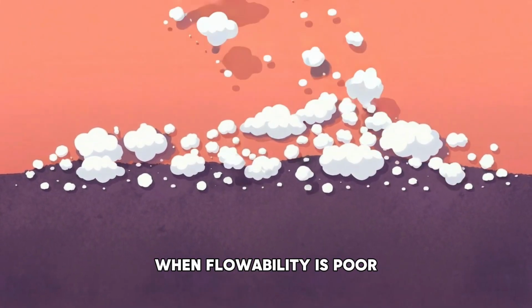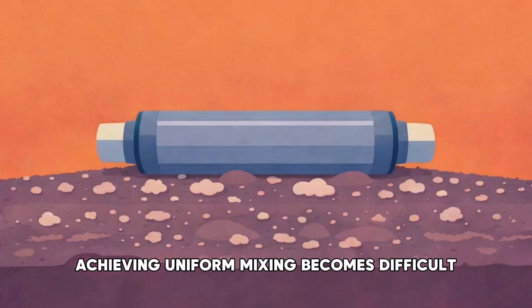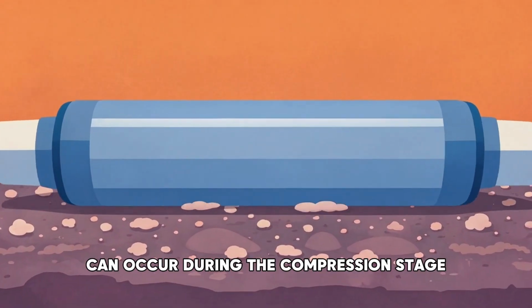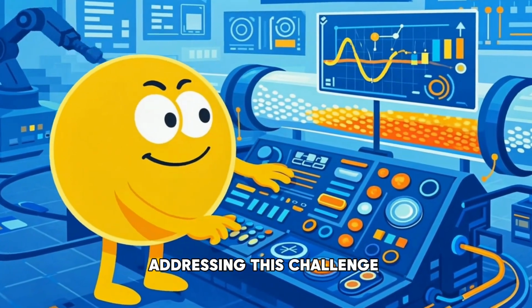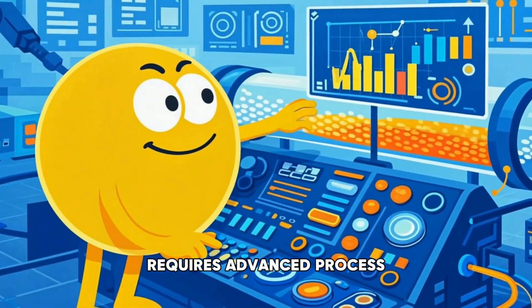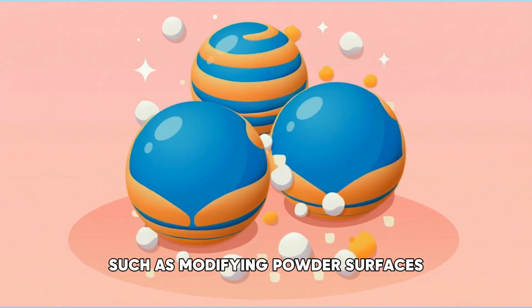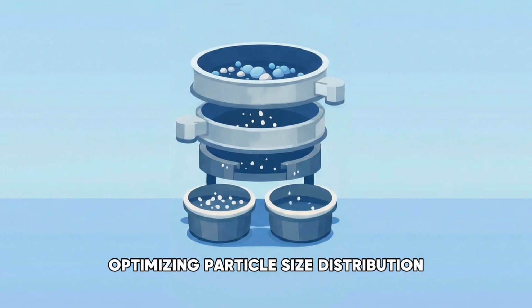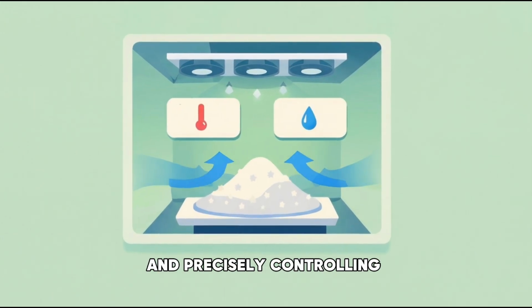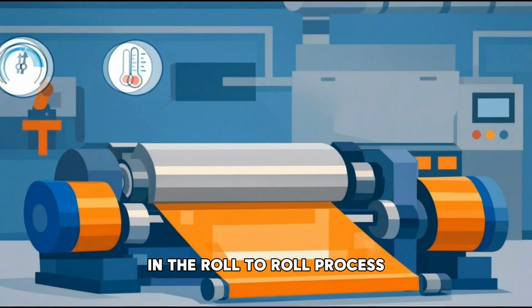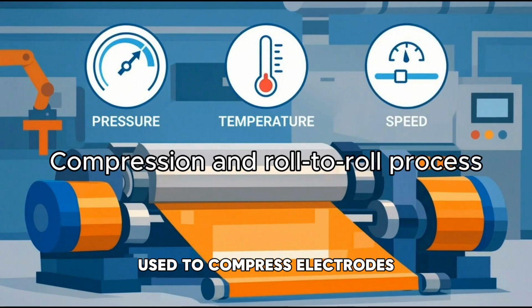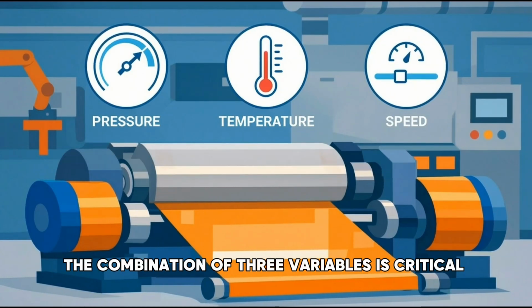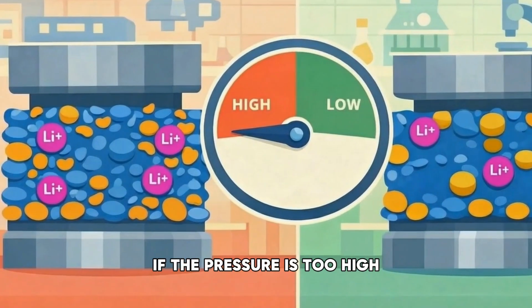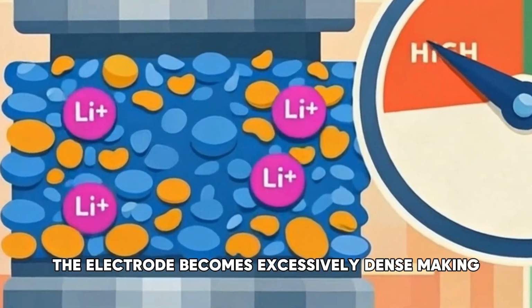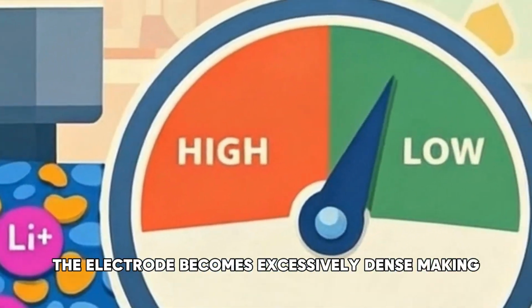When flowability is poor, achieving uniform mixing becomes difficult, and quality inconsistencies can occur during the compression stage. Addressing this challenge requires advanced process control technologies, such as modifying powder surfaces, optimizing particle size distribution, and precisely controlling humidity and temperature. In the roll-to-roll process used to compress electrodes, the combination of three variables is critical: pressure, temperature, and speed. If the pressure is too high, the electrode becomes excessively dense, making ion diffusion difficult.